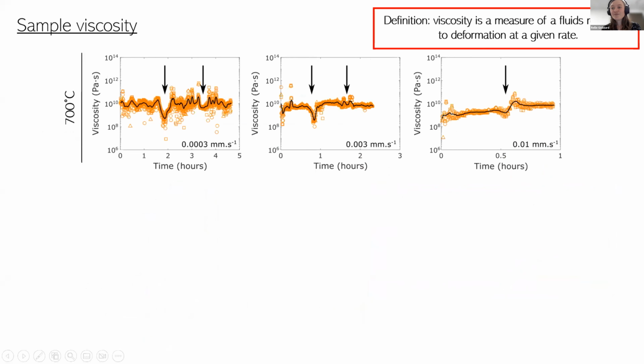So the best way of looking at whether we get any weakening or transient weakening is to look at basically viscosity, and viscosity is a measure of a fluid's resistance to deformation at any given rate. So in this case, because we're heating rocks up and they're able to flow, it acts similar to a fluid. And here we've got the viscosity on the y-axis plotted against time on the x-axis, and all these experiments are conducted at 700 degrees. And the black arrows are indicating when we're first going through the quartz to coesite transition and then back from coesite to quartz.